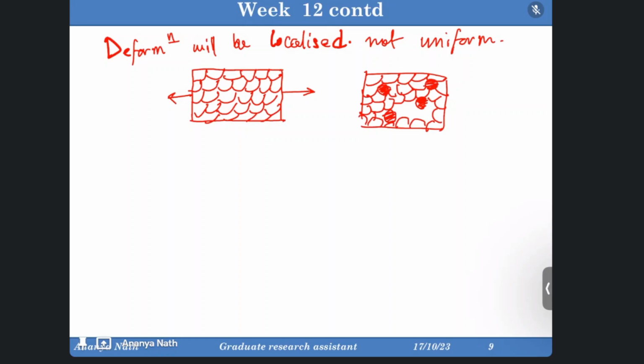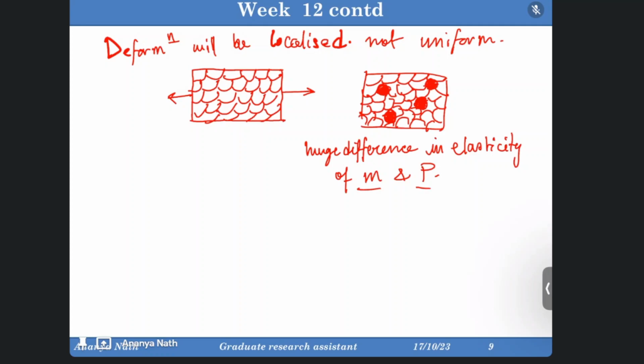When the load is applied, the load will directly go and affect the grain, the interface region. So obviously the interface will face more stress because there is a huge difference in the elasticity of the matrix and the particles. It's matrix, it's particle. So there is a huge difference in the elasticity, and due to the effect of load, the stress will be localized. So the deformation will also be localized.